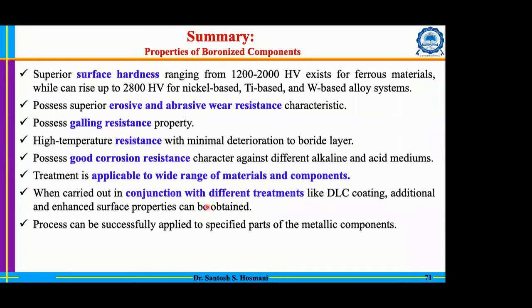Galling resistance is also extremely good. And deterioration of this boride is quite less, even at high temperature, due to the good oxidation resistance, and the corrosion resistance at the ambient environment, especially alkaline and acidic media, is also extremely good on the basis of our work as well as from the literature. And applicability, a wide range of materials can be boronized by using this technique. And DLC will be quite useful to get rid of some of the disadvantages associated with the boronizing. So that is what actually the summary of this.